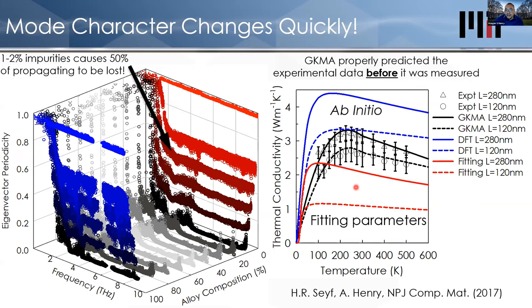When we did this for an alloy, this is that case I showed you where first principles doesn't agree with the experiments. Here are the fitting parameters, which don't agree with the experiments, and our Green Kubo modal analysis gets it spot on. What I'm most proud of with this data is that we did the theory before they did the experiments. So it was actually predictive. We predicted these curves and didn't change them, and they went and did the experiments and it was